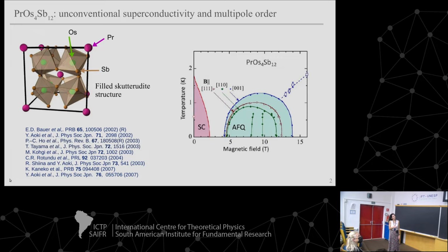This is temperature as a function of magnetic field. You can predict perhaps that magnetic field will be involved. But superconductivity is quite robust, 1.85 Kelvin and 2.2 Tesla for the critical temperature and field. And then at high magnetic field, there's a region of antiferroquadrupolar order. So this is not magnetic order, but quadrupole or multipole order. There's very weak magnetism in this system, which allows the multipole order to be dominant. So it was interesting for both of these reasons, particularly the superconductivity, as this was the first praseodymium-based heavy fermion system to be showing superconductivity, or at least unconventional superconductivity.